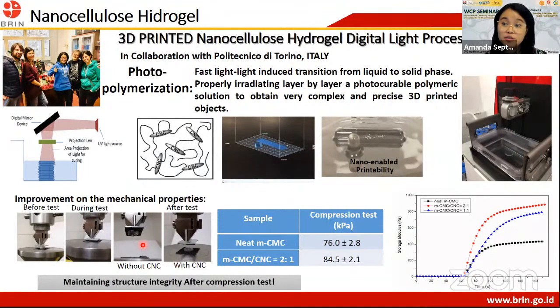Our previous visit showed that once we introduce the cellulose nanocrystal, when performing mechanical tests by fully pressing our hydrogel, we can see that without the CNC, the hydrogel can easily rupture. But for the hydrogel with the CNC, you can see that after the full compression test, it still maintains its structural integrity, which is really interesting, how it bounces back after the compression test. Based on the storage modulus, we can also see significantly that by introducing our nanocellulose, it enhances the storage modulus of the hydrogel.